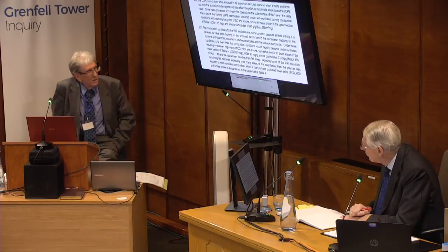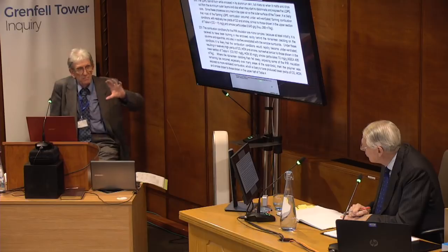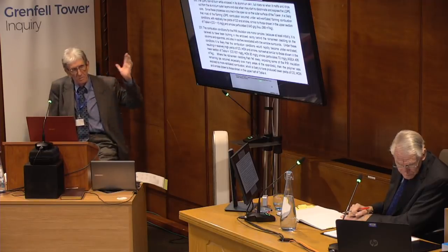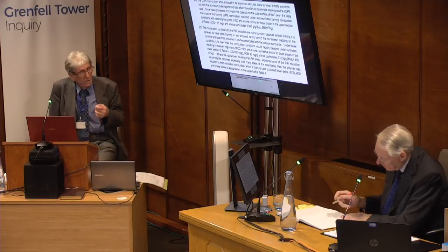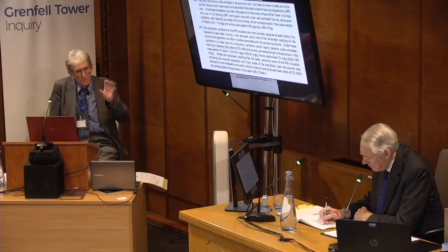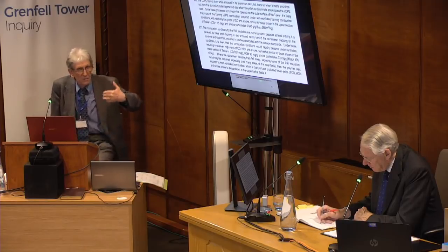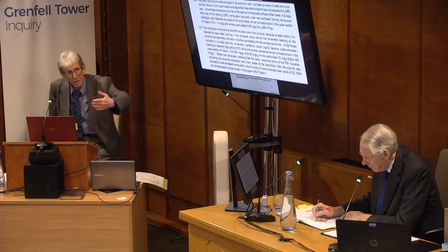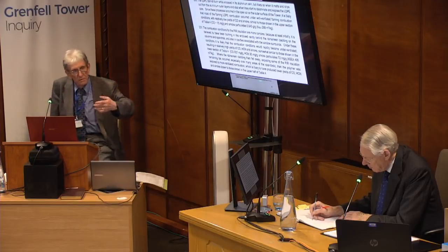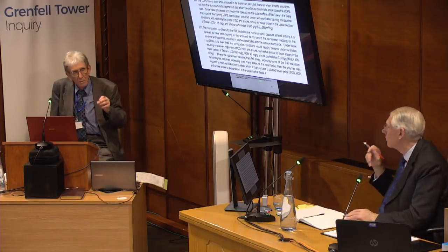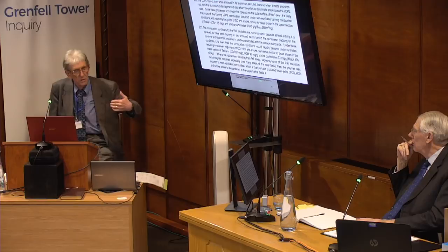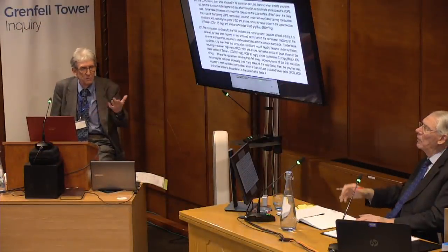Right, well, assuming that the same mass is decomposed, in the one case with the cladding intact and the other case with it having fallen away, then of course, if it remained intact, it preserves this cavity, which is more likely to lead to underventilated combustion. So if the rain screen cladding remains in place for a longer period, you would theoretically prolong the period of underventilated combustion of the PIR. If the cladding falls away at a very early stage, then you move to the more well-ventilated regime at an earlier stage for the PIR, I would say. We could do example calculations of this, should it be relevant.